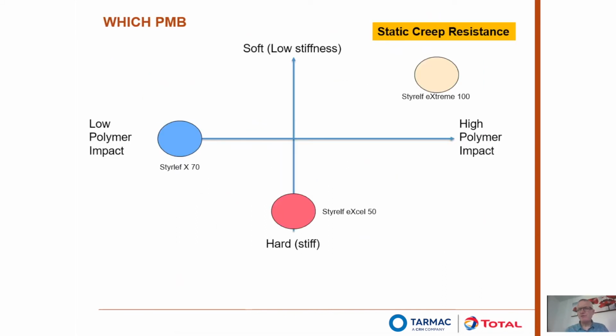So if we just return to that thought about static creep resistance and look at the type of bitumen that you want to be using in your asphalt in that sort of situation, that is all about bitumen stiffness. As I said before, the polymer won't help it. If it's an elastomeric polymer, it's not going to help it much because it's not getting time to recover. And that's how the elastomeric polymers act. So something like X70 is a little bit too soft. Something like Styrelf eXcel 50, because it's a harder, stiffer bitumen, that's going to work reasonably. Styrelf eXtreme 100 this time won't work because it's soft. It's low stiffness. And static creep resistance is all about stiffness. So the stiffer you go with your bitumen, the better the performance.